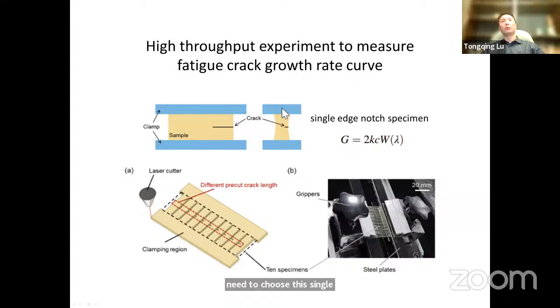The energy release rate for this configuration is here, because this kind of configuration is easy to arrange in parallel. Here we arranged 10 specimens in parallel, with each specimen having a different pre-cut crack length. This means when we apply the same stretch, each specimen is subject to a different energy release rate. In fact, it may not be called high throughput because we only have 10 specimens, but we found out 10 specimens is actually enough.